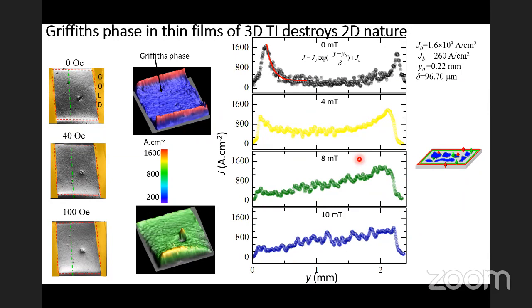Time reversal symmetry breaking causes a suppression of these edge currents, and even these currents are decreased, and it tries to make the conductivity of the system a little bit more uniform. And so this is the reason why we believe that in thin films of 3D topological insulators, you never see the 2D nature of the surface state: because of the presence of disorder, the 2D state of electrons already goes into the Griffiths-like phase.